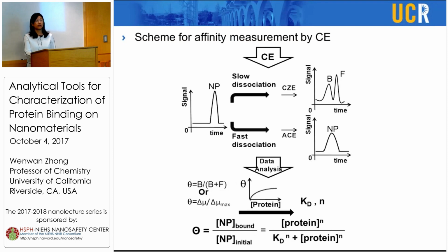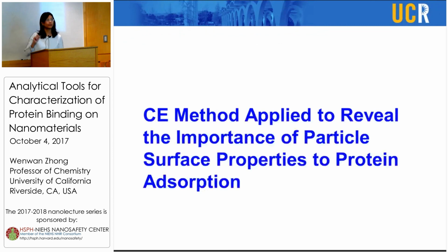Another scenario is that the dissociation rate is very fast, so the complex is not stable during the separation process. So we have to put the protein into the separation buffer, and then we can observe the mobility shift of the nanoparticle when the protein is present in the buffer. The mobility shift of the nanoparticle can then be used to calculate the bound ratio, and then we can do the Hill equation fit to find the Kd.